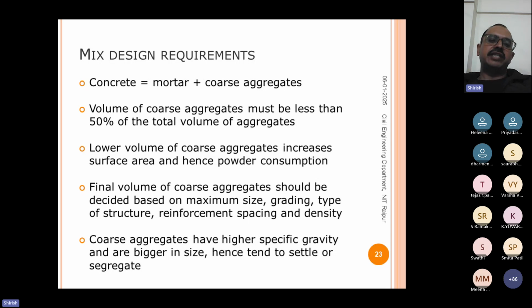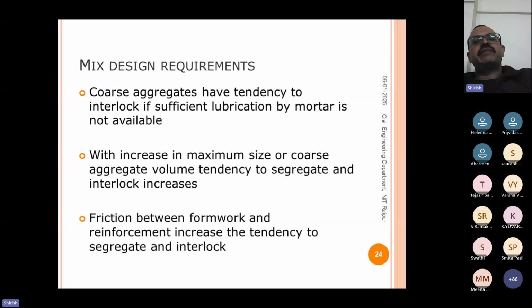Final volume of coarse aggregate should be decided based on maximum size. Generally, it is difficult to manage larger sized coarse aggregates. Though in the past self-compacting concrete has been designed with 40 mm aggregate as well, generally people prefer 12 or 20 mm aggregates for self-compacting concrete. Coarse aggregates have higher specific gravity and are bigger in size, hence tend to settle or segregate. Coarse aggregates have a tendency to interlock if sufficient lubrication by mortar is not available. This interlocking is a very important aspect that we can call segregation. We will be discussing how to check that segregation part.